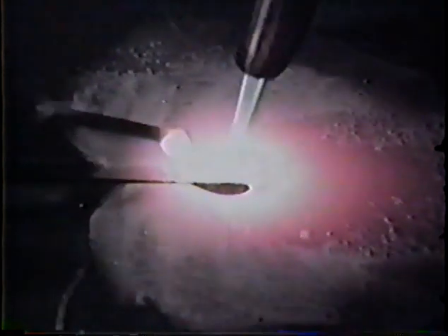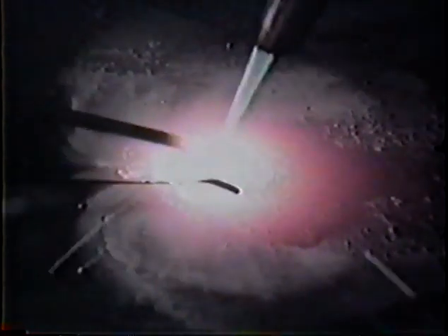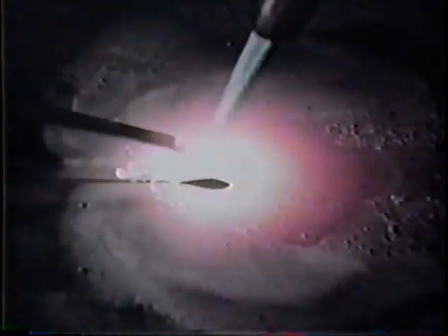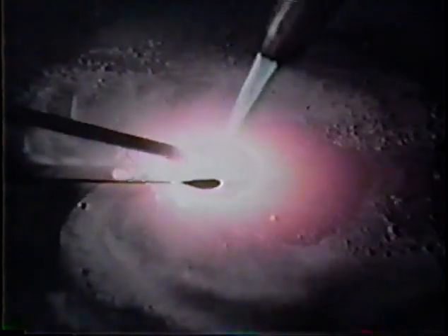If you're blowing a hole from too much heat as you try to progress with the weld, then decrease the angle of your torch slightly to decrease the amount of heat and add sufficient filler material.